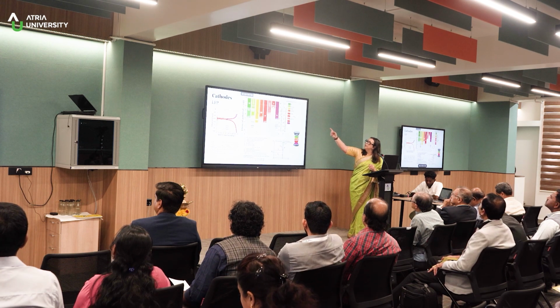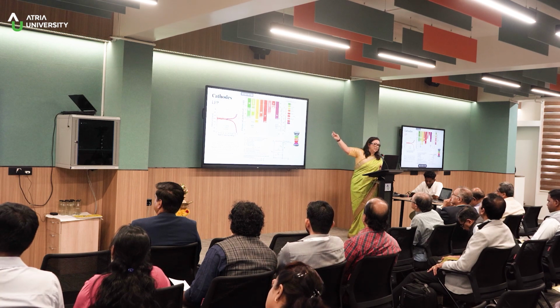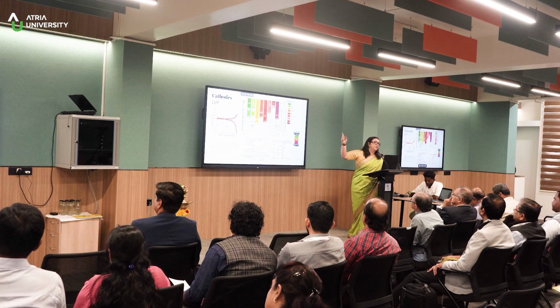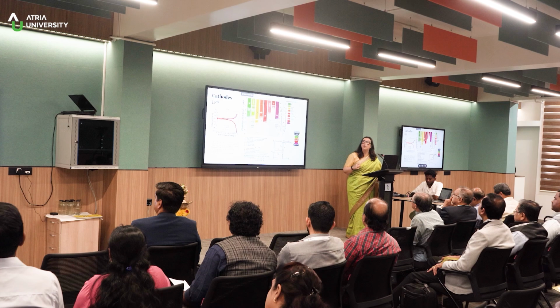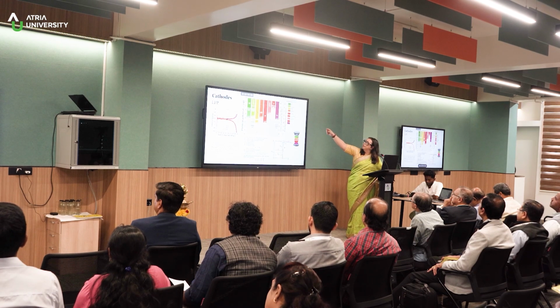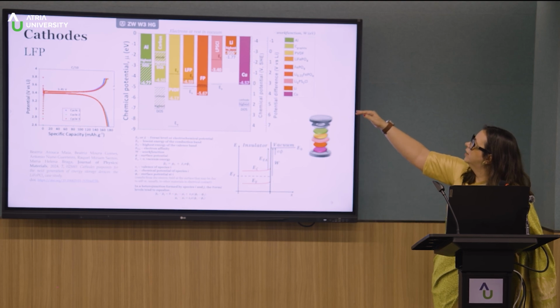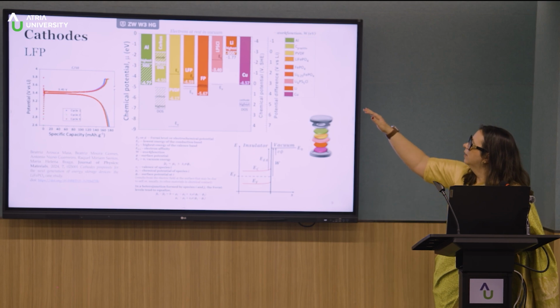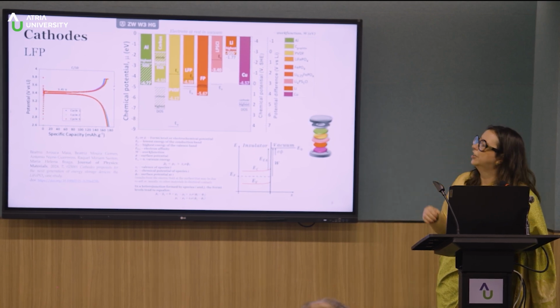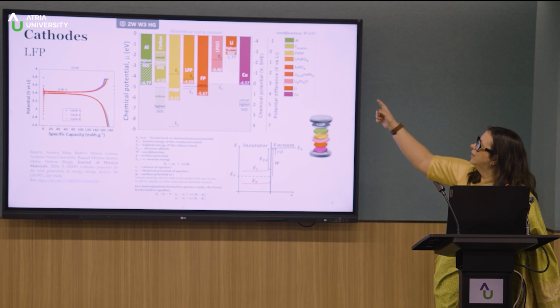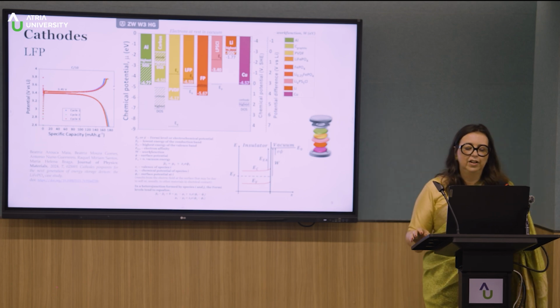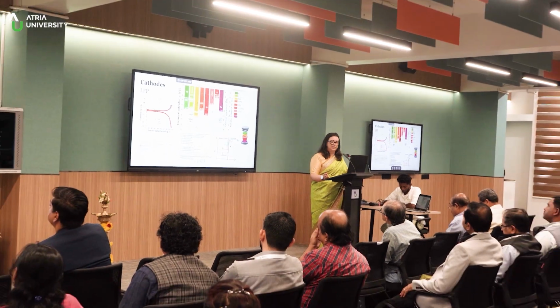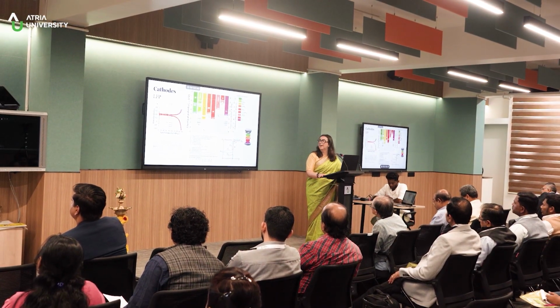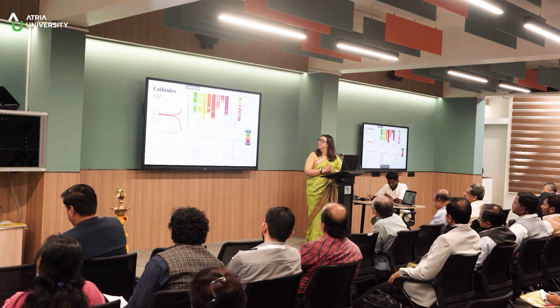with this electrolyte, LPSCl, we know that there is a high chance that there will be a reaction between lithium and LPSCl. Why? Because the chemical potential of the lithium is there, 1.39, and the minimum energy of the conduction band is actually lower than the potential of the lithium. So what is going to happen is that the lithium electrons will tunnel to the conduction band of the electrolyte.